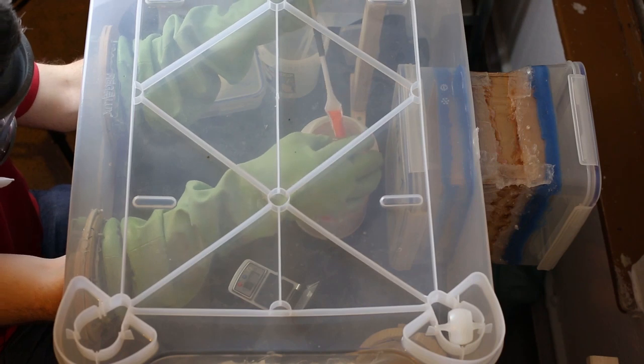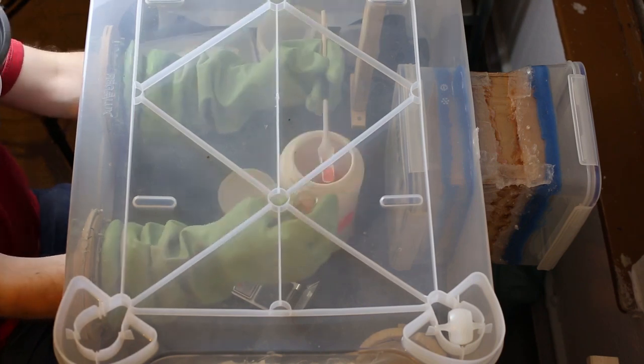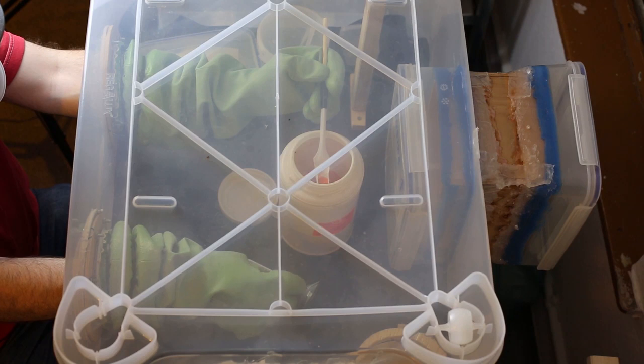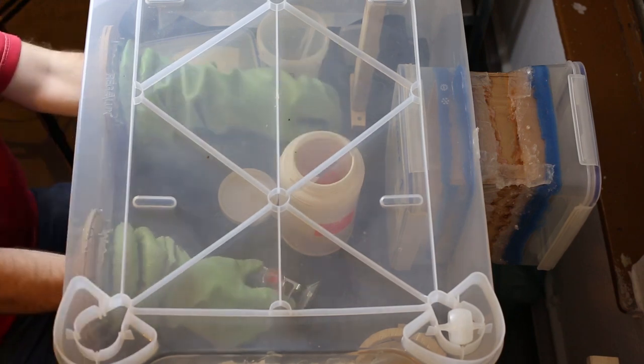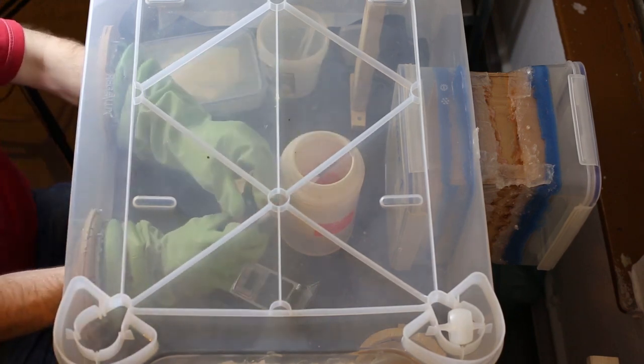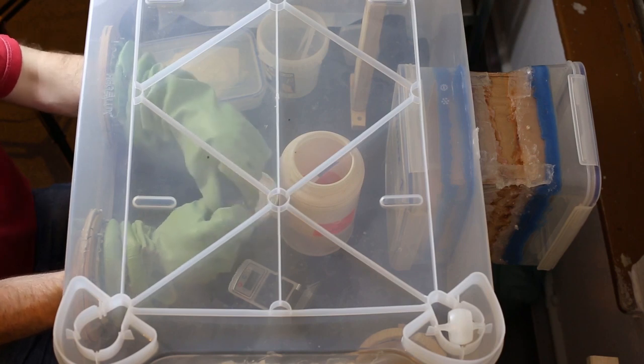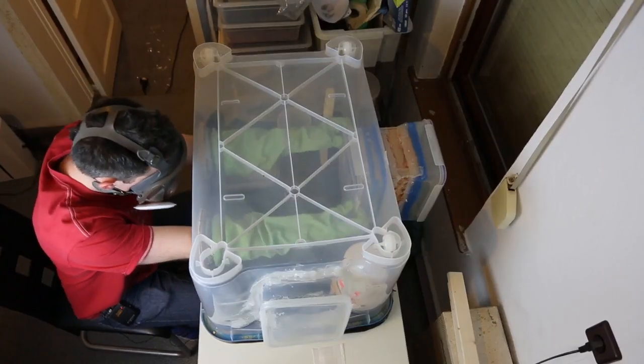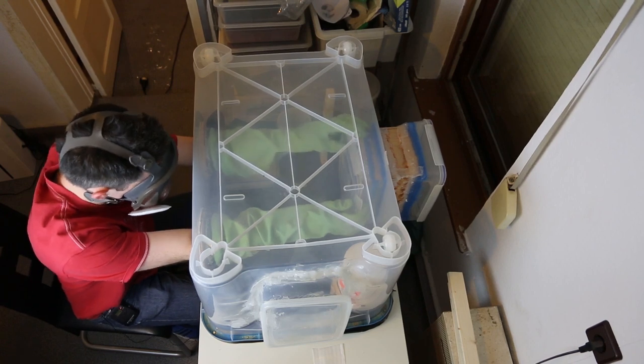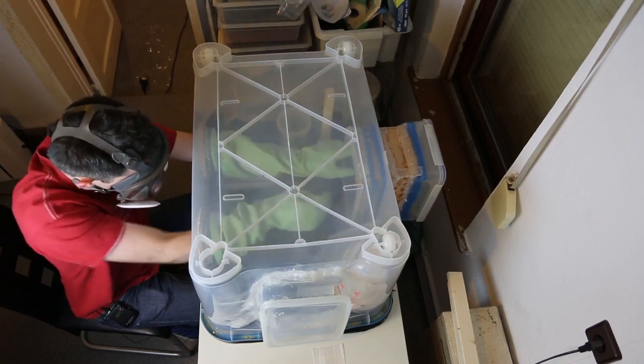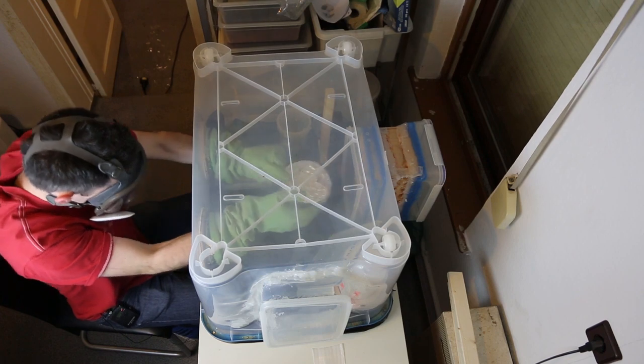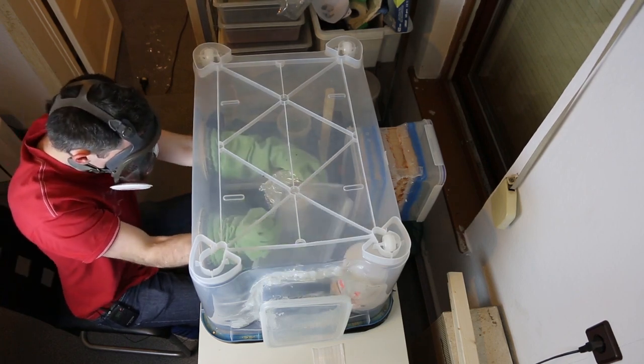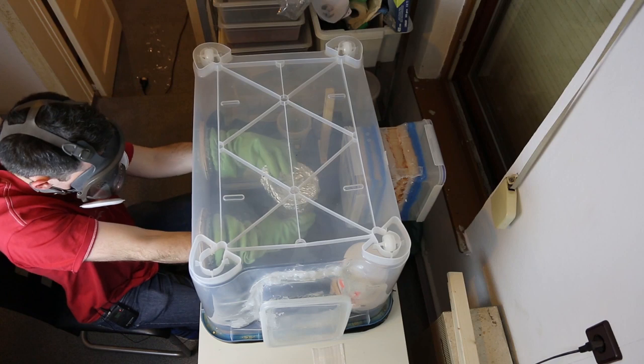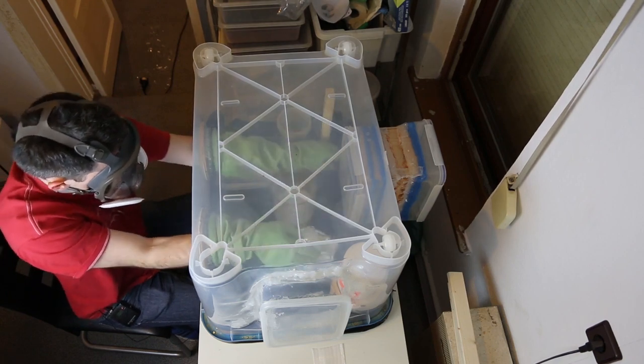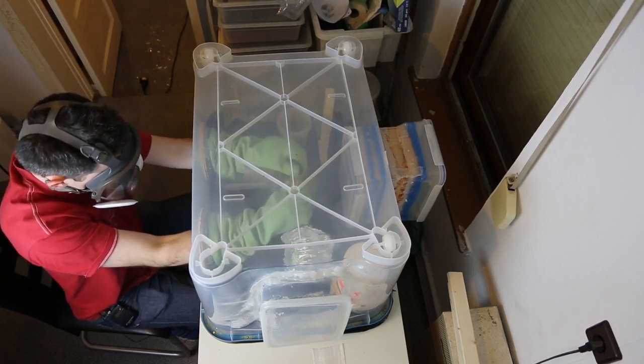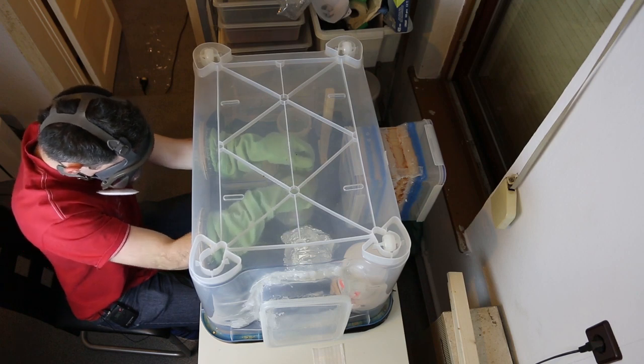With a spoon and a little electronic scale, I measure 8 grams of ammonium dichromate and fill it into a little glass bottle. As you can see, the space in the glove box is very cramped. So I first measure the powder, and then in a second step, I put the powder into a beaker. For that, I reopen the airlock and bring in the beaker with the warm liquid gelatin. I remove the tinfoil dust cover and pour in the 8 grams of ammonium dichromate.